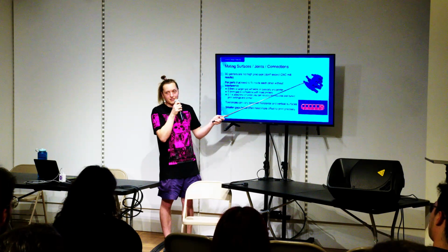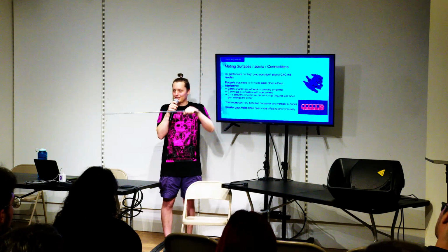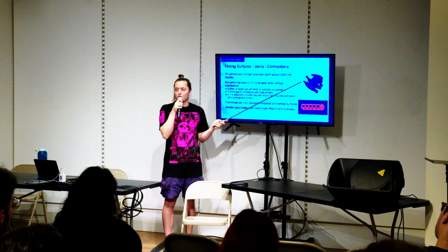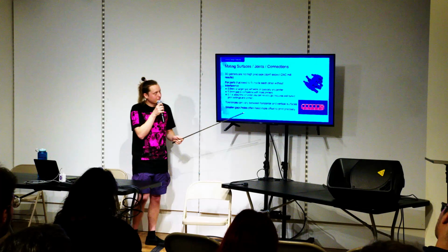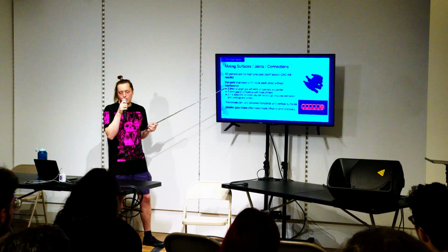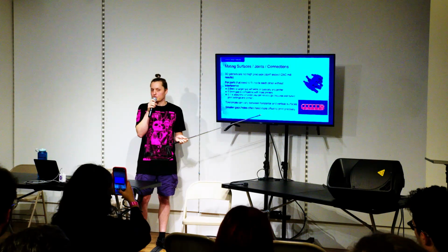In this case, the 0.1 and the 0.15 don't move at all. They're completely fused into this print. And the 0.2, I had to use a pair of pliers to snap it loose, but once it was snapped loose, it was able to move. So you can print one of these and figure out what your printer is able to do. And then this is kind of a general rule of thumb: a 0.3 millimeter gap between pieces works for almost all printers, and a 0.5 millimeter gap or larger works on everything.